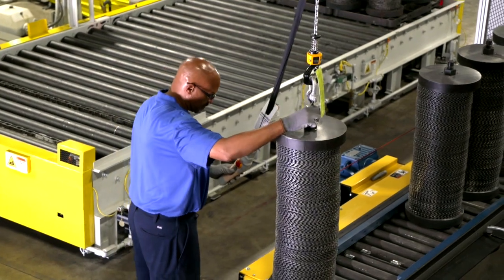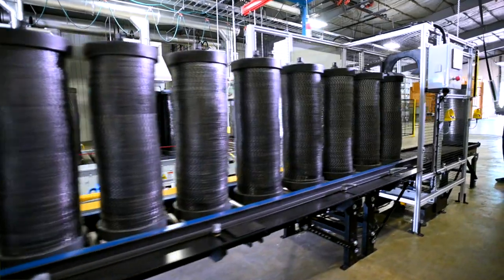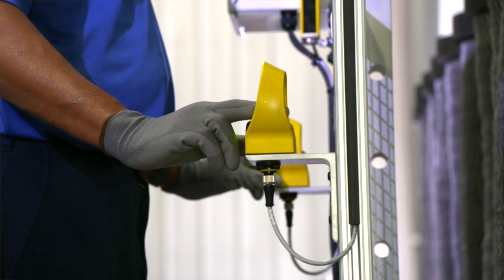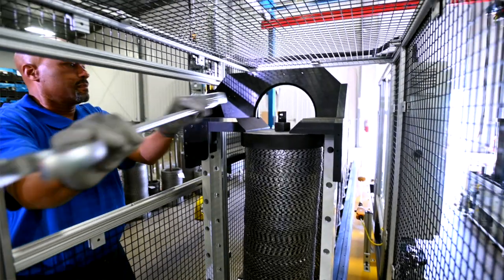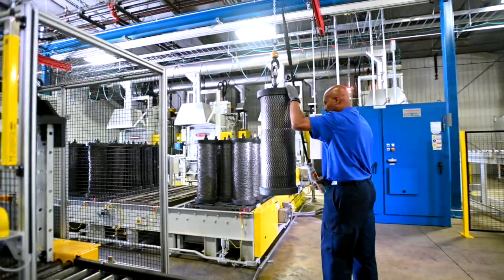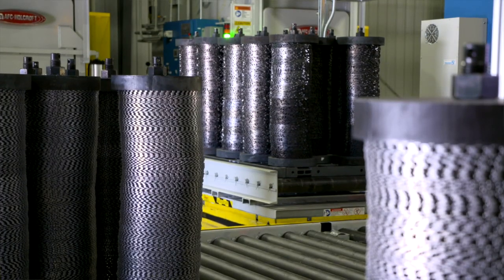At this facility here at Feintool Cincinnati, we are doing heat clamp tempering. It's a stress-relieving process that allows us to ensure flat product to our customer. We put those through a compression, about 5 tons of compression force, and then we hold those tight and compress through the process. From that press operation, the parts are moved onto trays, and then the automation of our process takes over from there.